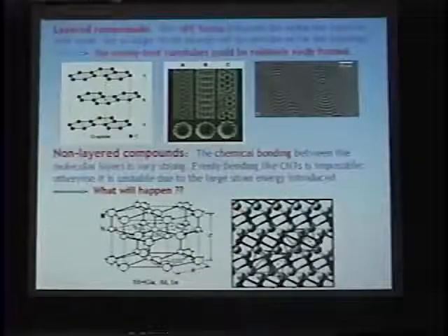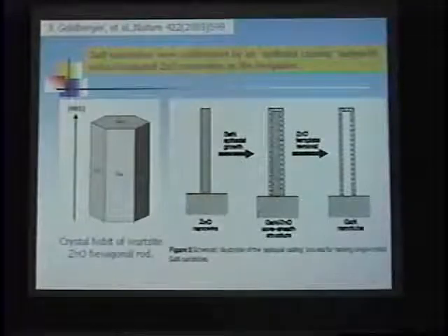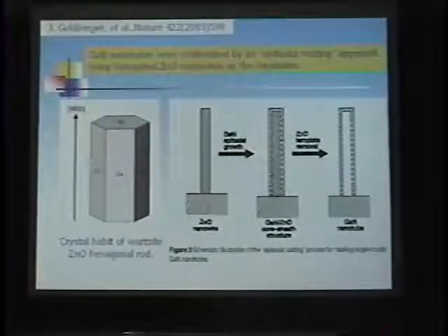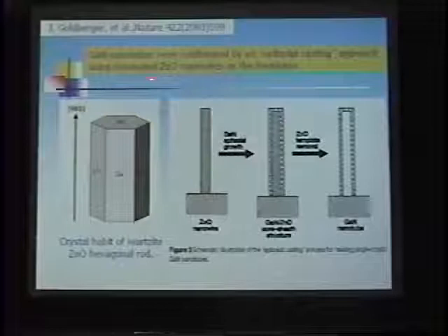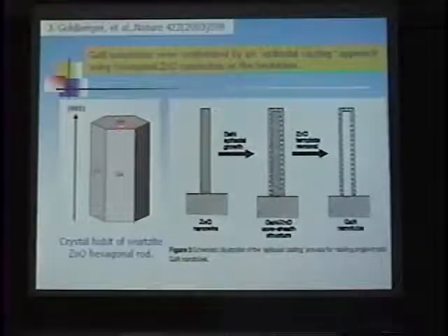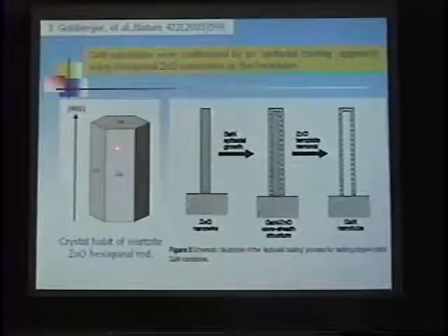Then what will happen? In 2003, the Berkeley group synthesized gallium nitride nanotubes. These nanotubes were synthesized by an epitaxial casting approach, using hexagonal zinc oxide nanowires as a template. As we know, the zinc oxide nanowire has such crystal habits. They grew gallium nitride epitaxially on the surface of the zinc oxide, then removed the internal zinc oxide, so they could get gallium nitride nanotubes with a hexagonal cross section. This is very natural since the zinc oxide template has such a morphology.